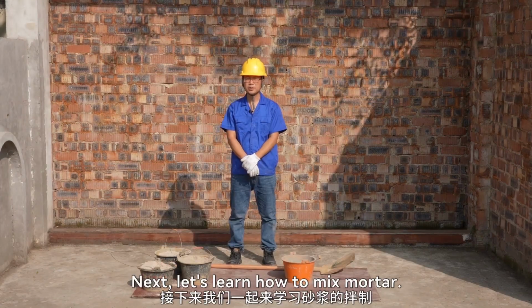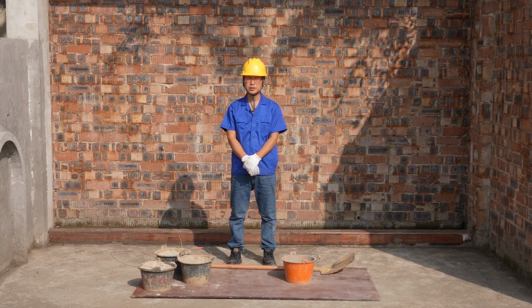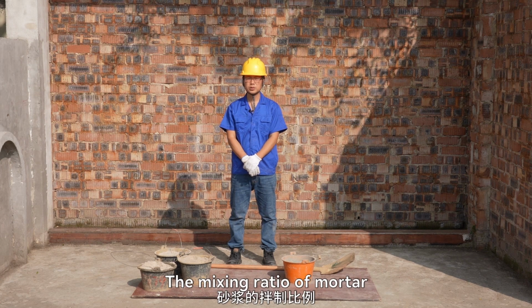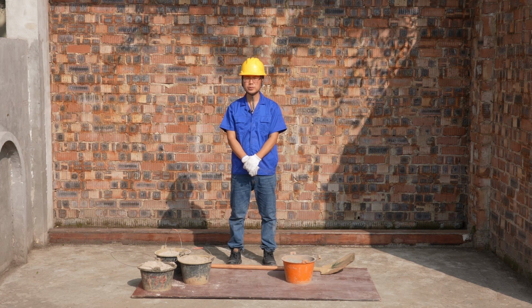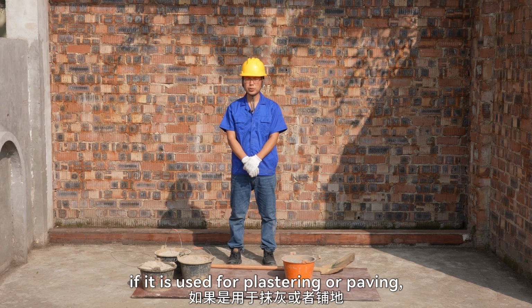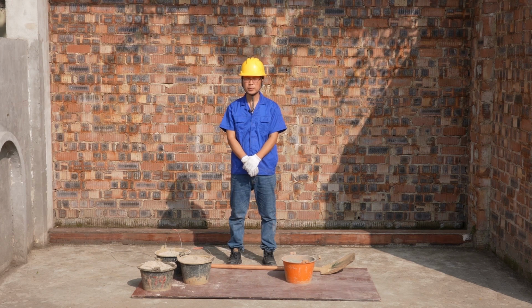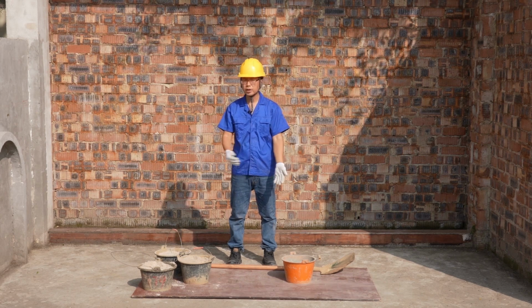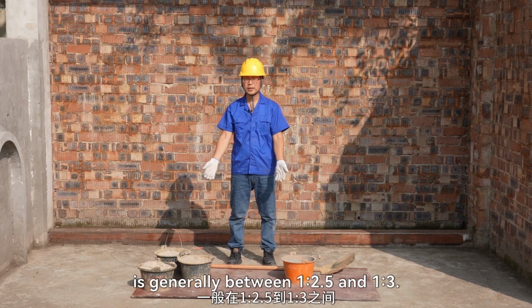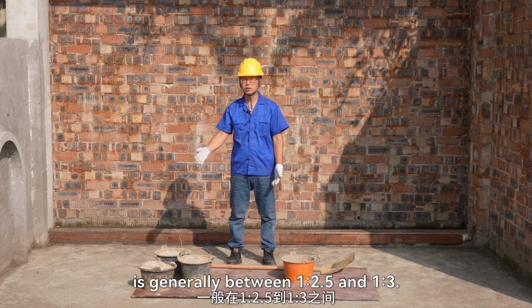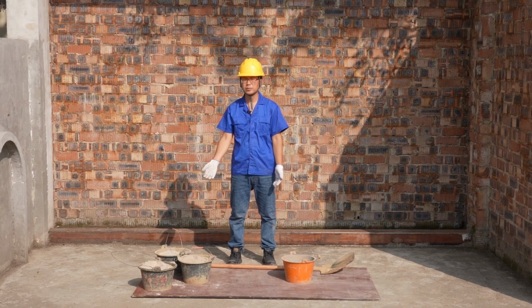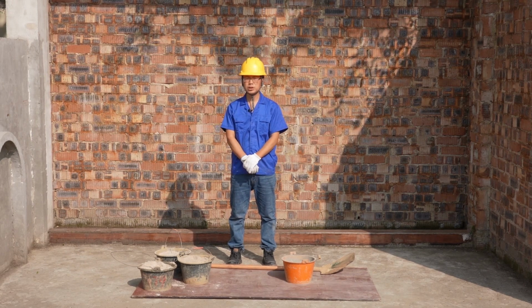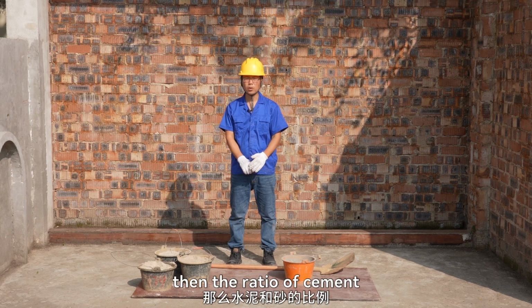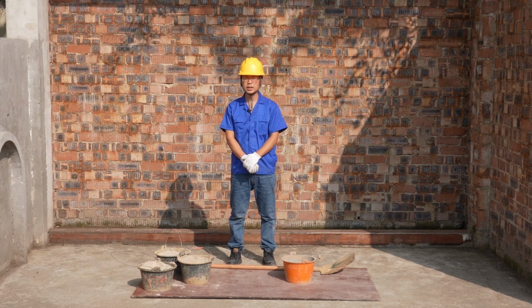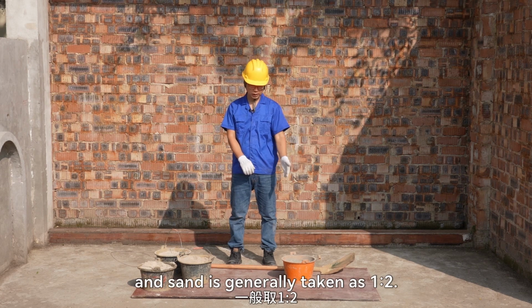Everyone, next, let's learn how to mix mortar. The mixing ratio of mortar mainly depends on the use. If it is used for plastering or paving, the ratio of cement and sand is generally between 1 to 2.5 and 1 to 3. If it is used for masonry, then the ratio of cement and sand is generally taken as 1 to 2.